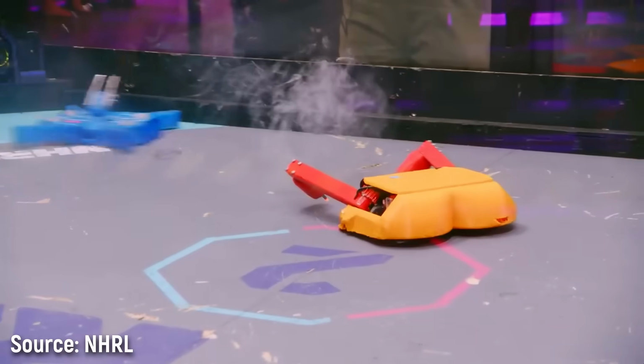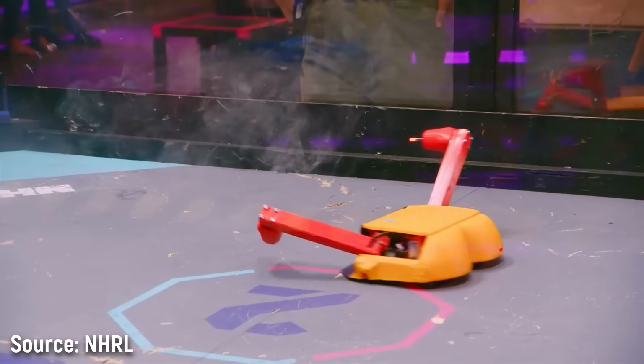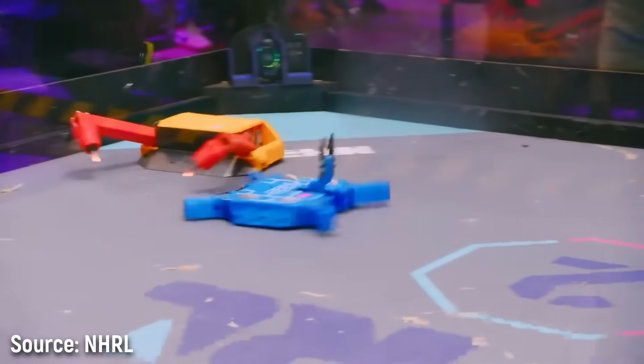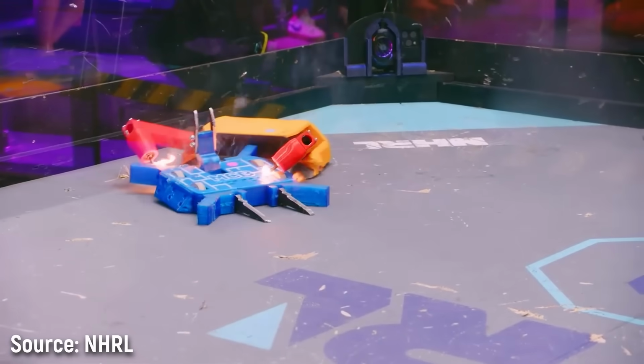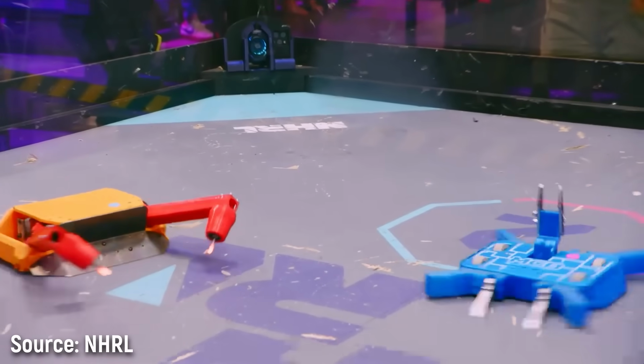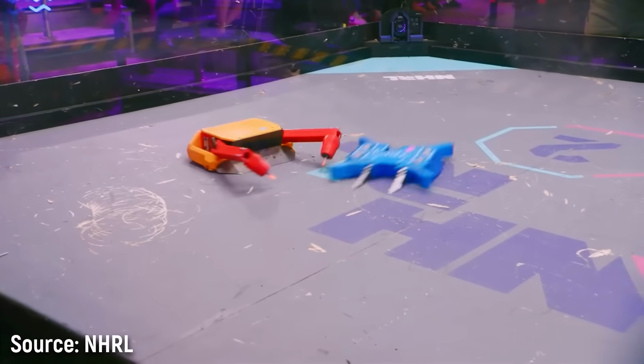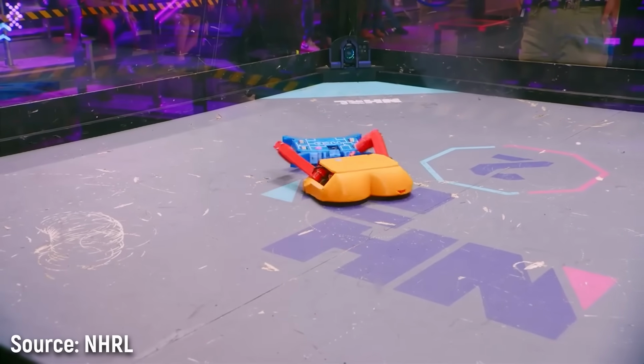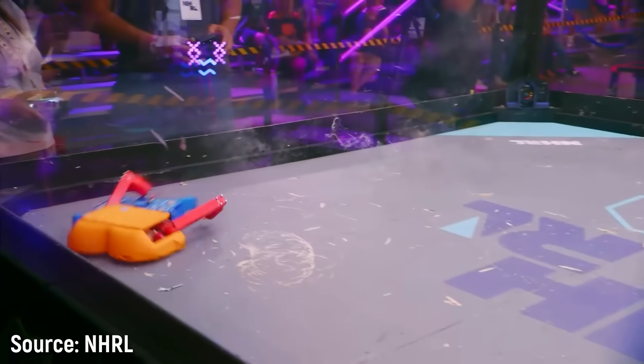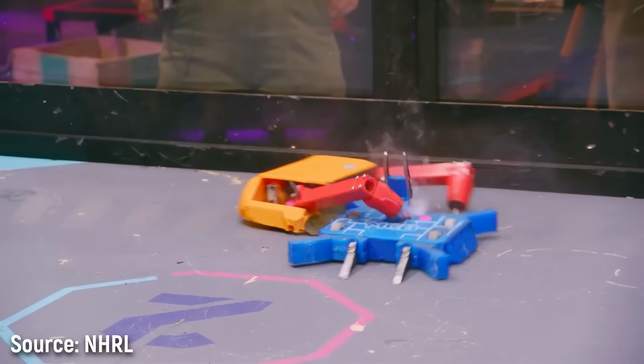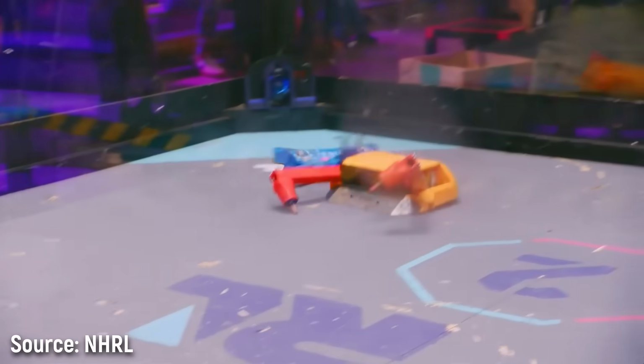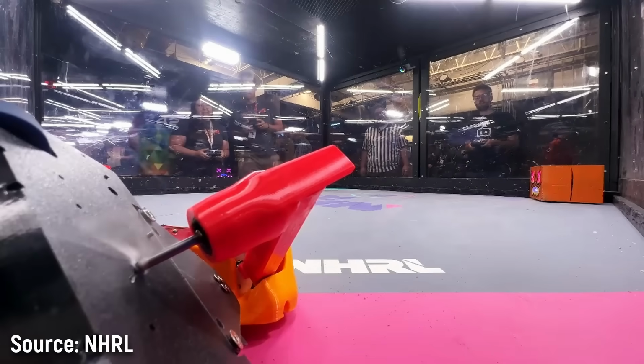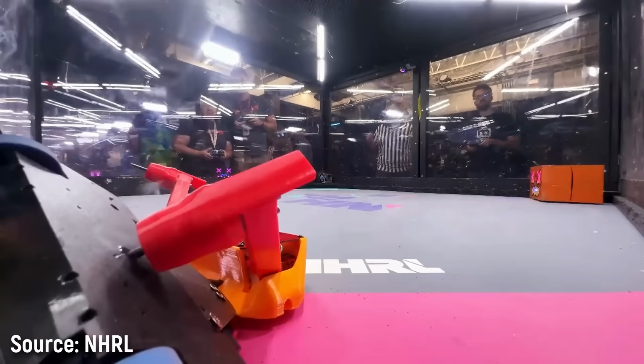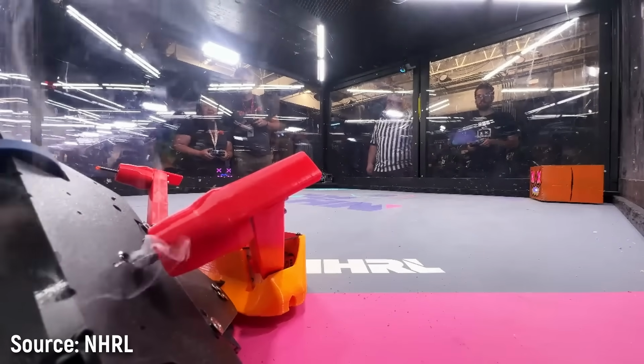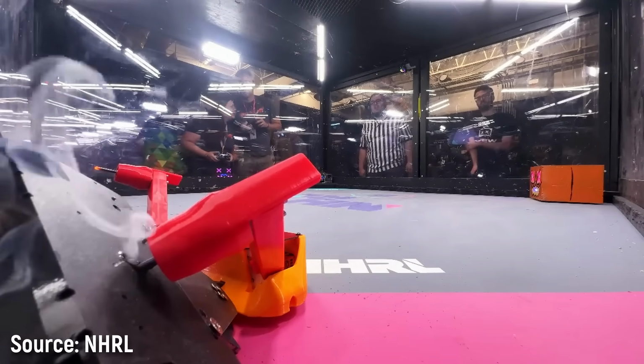But that's not to say it can't happen, because there's a combat robot called Buffalo Wings, which uses automotive glow plugs as heat weapons, and they get super red hot, heating up to around 1000 degrees or so. And you can see in its fights that 3D printed plastic can indeed ignite instantly on contact with temperatures this high. I saw a lot of melting across all of its fights and plenty of flame as it did so, but as far as I can tell, that fire rarely, if ever, sustains itself once the heat source is removed.